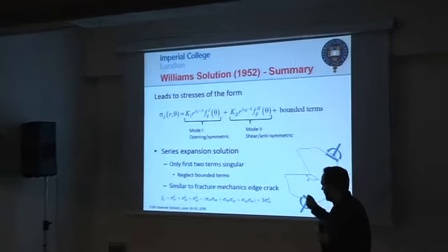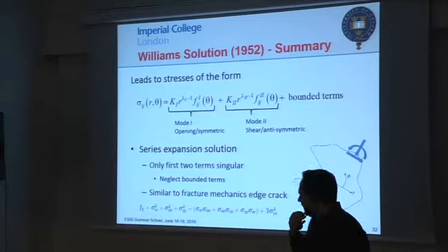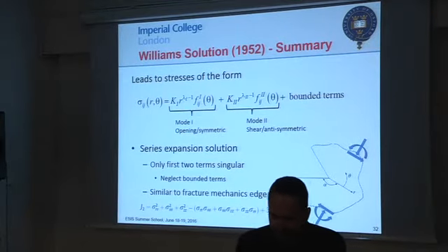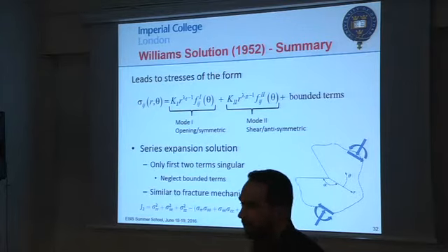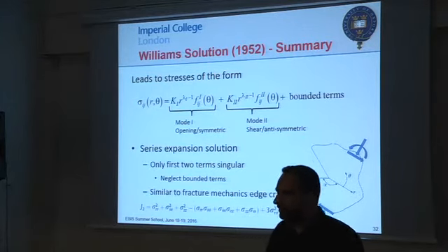In this series expansion solution, we just took the first two terms. They're singular up to a point. One of them we know can be bounded, but we can neglect all the other bounded terms for the time being. And it's really a solution which is very similar to a crack solution. The only thing that changes is that these exponents and these factors change with the angle.